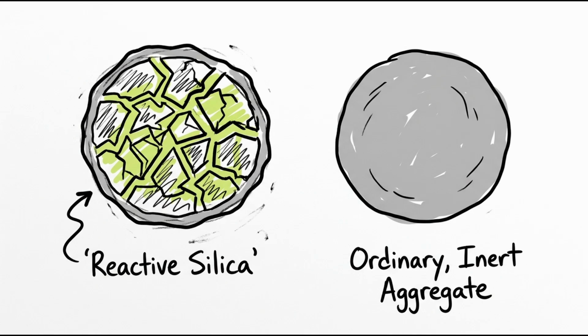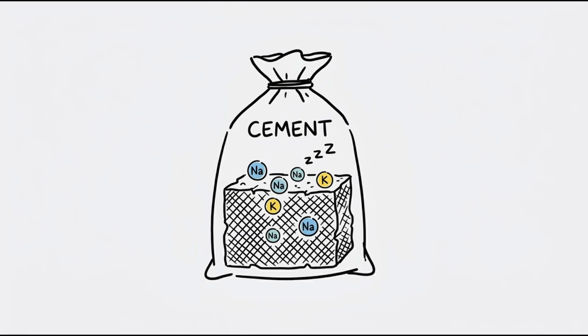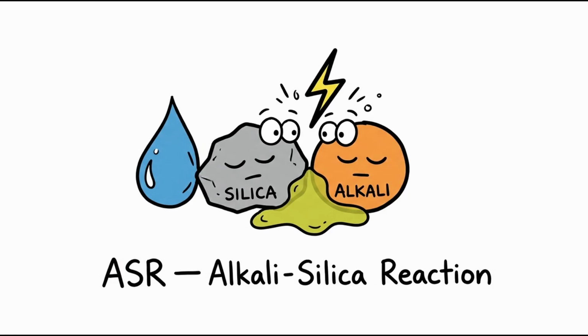Remember, aggregate is just crushed rock, and rock, chemically speaking, is not inert. Some rock types, certain forms of quartz, chert, opal, or volcanic glass, contain a specific mineral structure, reactive silica. Meanwhile, cement contains alkalis, sodium and potassium compounds, as a natural byproduct of how cement itself is manufactured. Normally, these alkalis just sit quietly inside the hardened concrete, doing nothing dramatic. But introduce moisture. And any road is guaranteed to have moisture, and those alkalis can start reacting directly with the reactive silica in the aggregate. This is the alkali-silica reaction, or ASR, and the product of that reaction is a gel.